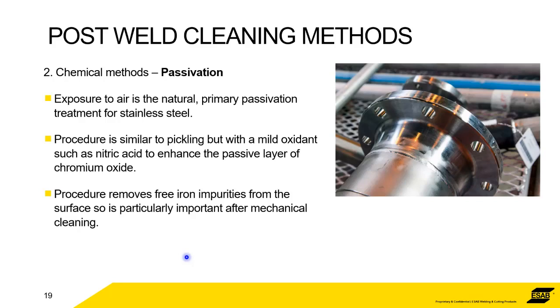But if you treat it with this mild nitric acid, HNO3, there's oxygen in there, and that will encourage, if you like, the chrome to form chromium oxide on the surface. It's acid, so it will remove the iron from the surface. So it's more common to be used after some kind of mechanical cleaning.